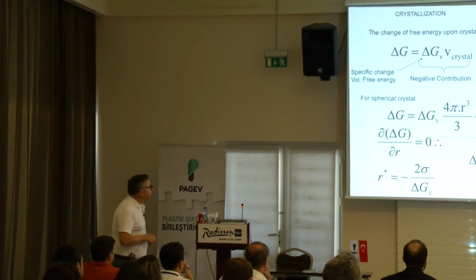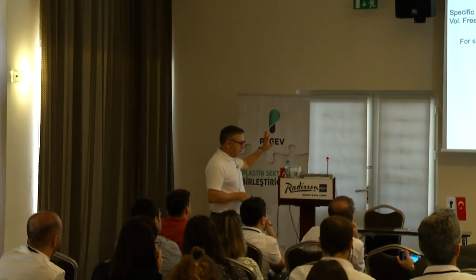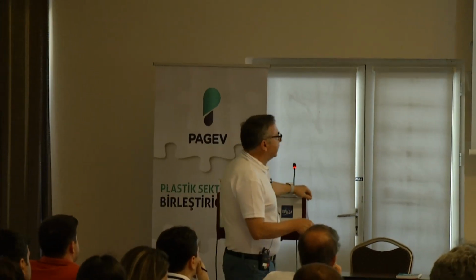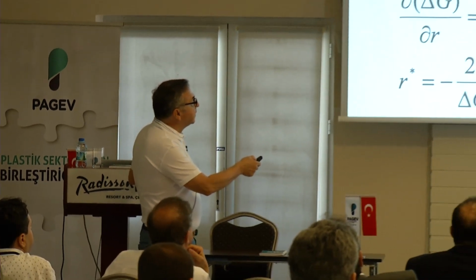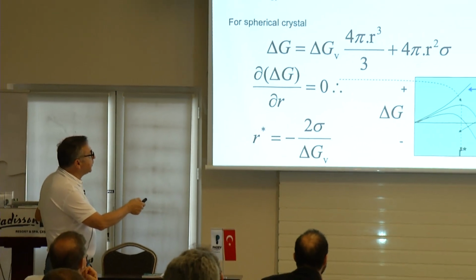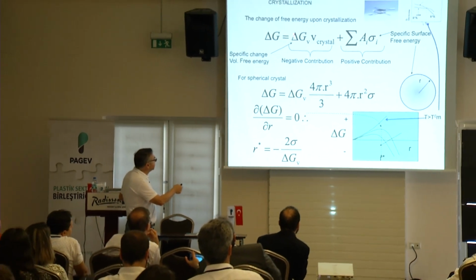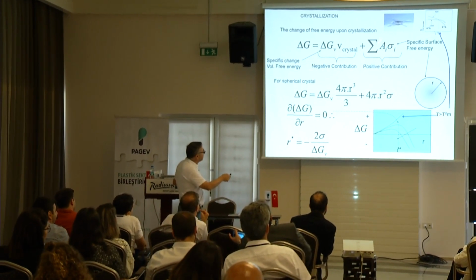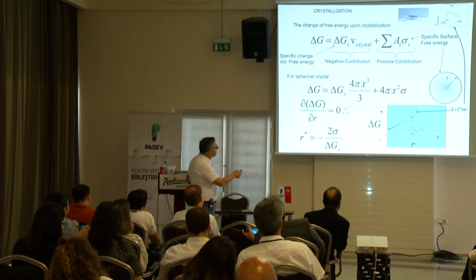Right? So these are not scary equations, but let me explain. We have a crystal, a spherical growth crystal. We just assume it's spherical growth, and the radius is r, OK? And it just simply gradually grows. So we have a volume contribution to the free energy. This is the volume contribution. So volume basically says when you crystallize from a liquid, and we saw in the curve, it's negative. We are below the equilibrium melting temperature, so this is always negative. The surface contribution is always positive. So they fight with each other.